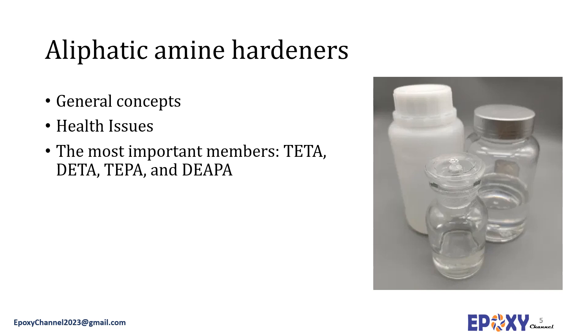The amines employed in the curing of epoxy resins can be divided into three groups: aliphatic amines, aromatic amines, and cycloaliphatic amines. Aliphatic amines contain only hydrogen and alkyl substituents. They are the most commonly used curing agents for epoxies — usually fast curing, low viscosity, and resulting in good chemical resistance. Among different amine hardeners they are the most reactive, but they are often modified to eliminate volatility-associated problems. They can be pre-reacted with part of the epoxy resin to form a polyamine adduct. These amines often have a short pot life of only 30 minutes to 2 hours.